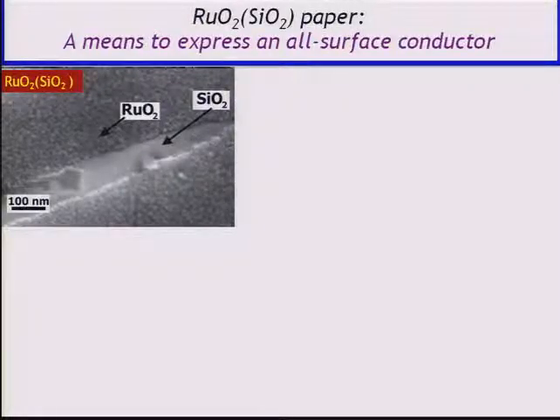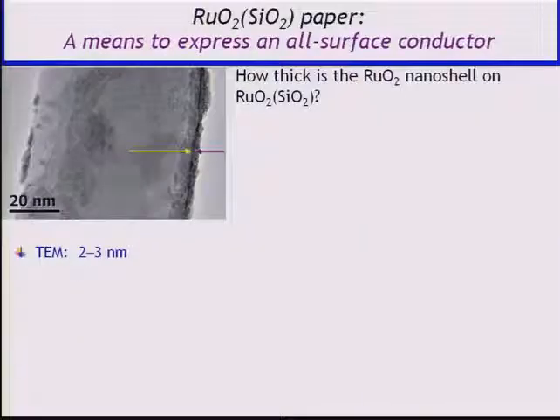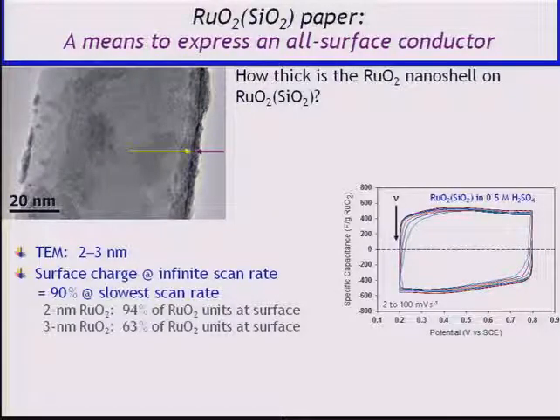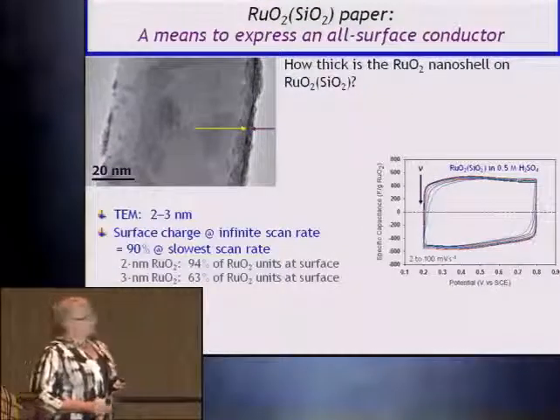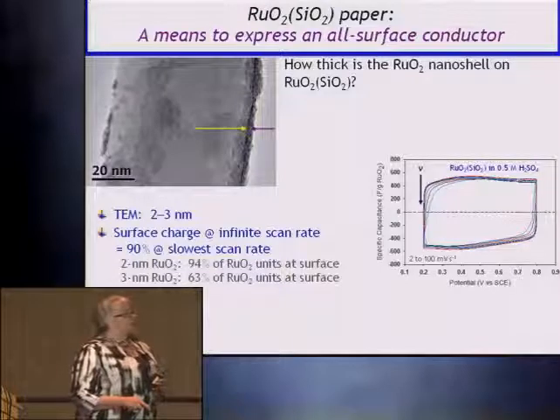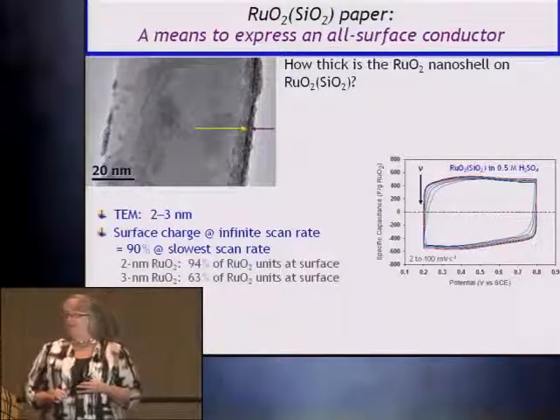In the high-res SEM, you see like packed sand at the beach, very small nucleates of the RuO2, and every now and then we see a break in the film so we can actually see down to the silica fiber and get a really high-quality image. But we really wanted to know how thick this nanoshell was. By TEM, on the very thinnest fibers, you can see something that's about 2 to 3 nanometers thick. But again, electrochemistry turned out to be the better way to do this. Half-molar sulfuric acid, the ruthenia wrapped silica fibers in the paper, and this is its current voltage curve. It's a beautiful charge storage capacitor. And we're going between 2 and 100 millivolts per second, and it's not changing very much as a function of scan rate.